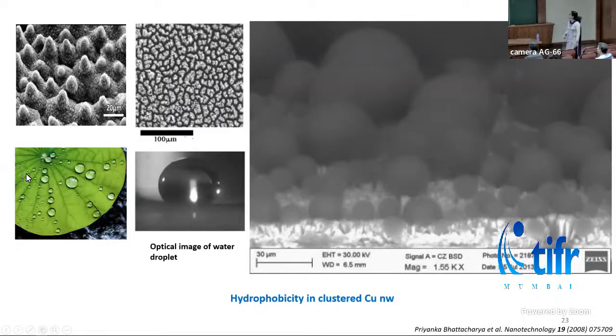We all know the lotus leaf is hydrophobic in nature, but what makes it hydrophobic? So there are nanostructures on this leaf which make it hydrophobic. There are efforts being made to modify surfaces to make them hydrophobic. So can we synthesize a similar surface in the lab? Yes, so these are copper nanowires grown in a porous anodic alumina template, and after removing the template, they form a cluster. And here is an optical image of a water droplet standing on these clustered copper nanowires, which tells us, yes, this sample is hydrophobic in nature.